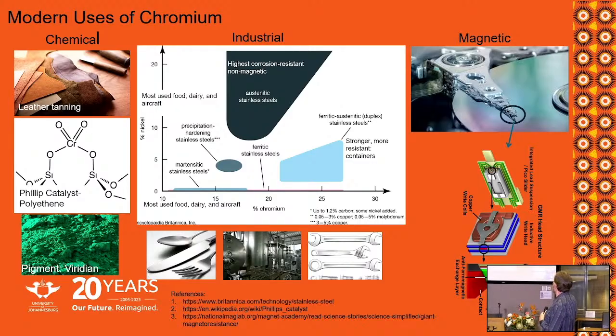And then of course in industry, where chrome is mainly used is to make stainless steel. In this case, depending on how much chrome or nickel you add, you can get 5 different classes of stainless steel. In stainless steel itself, there are something like 100 different grades, broken down primarily into these 5 classes. Do you want stainless that's very corrosion resistant, non-magnetic, or do you want a very strong stainless? It's a mix. Of course, it's not just a mix of nickel and chrome. It's also a mix of other metals. Sulfur and carbon are sometimes added to a certain percentage.